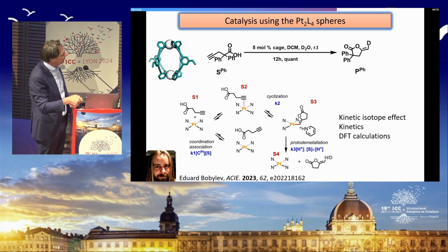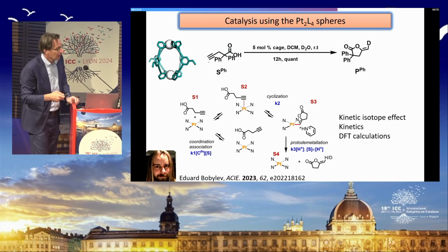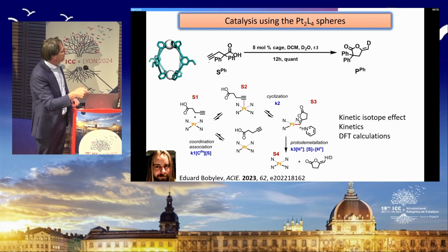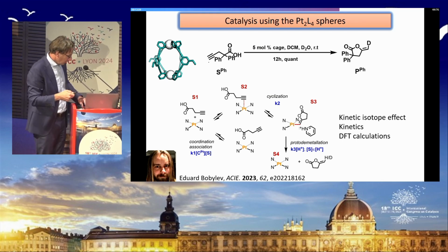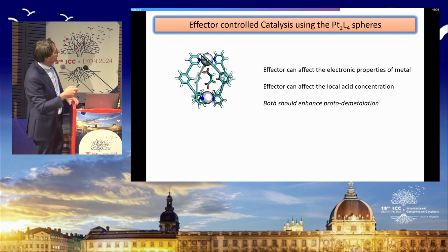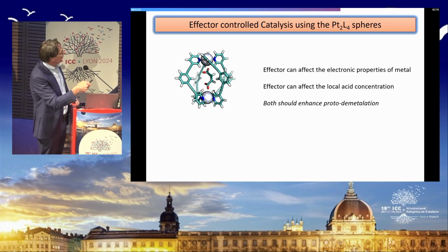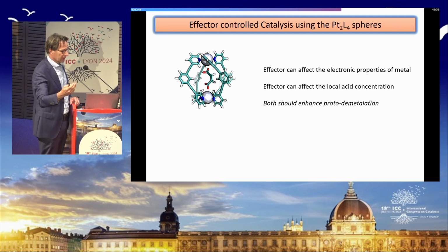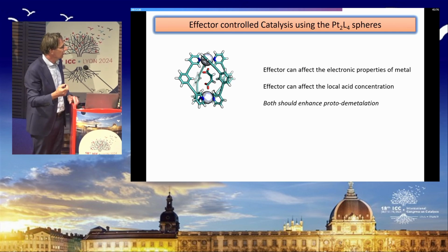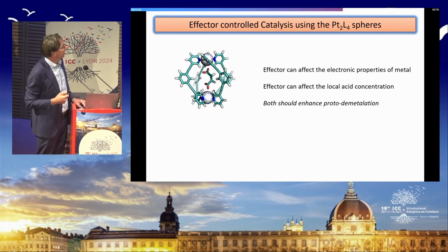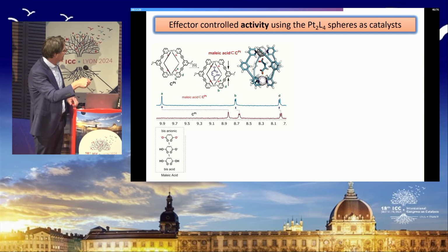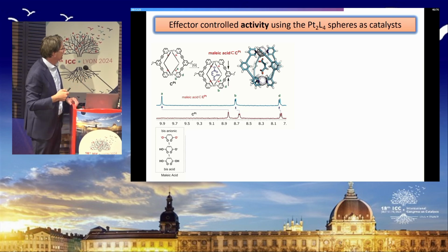We studied this mechanism with kinetic isotope effect, kinetics and DFT calculations. And what we observe is we have alkyne coordination, then a sort of insertion into the platinum and deprotonation of the alkyne, and then we have a rate-determining proto-demetalation. So from this rate-determining metal deprotonation, we thought, okay, if we have an effector over here, then the effector can change the electronic properties of the platinum and thereby induce higher or lower reactivity. But also the effector can change the local acid concentration, and both should lead to enhanced proto-demetalation and therefore an overall higher reactivity.